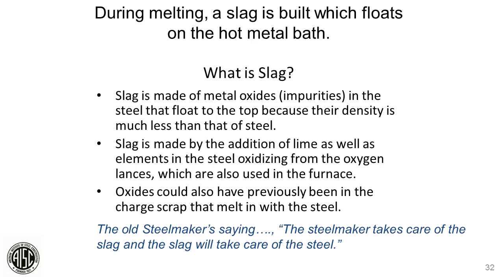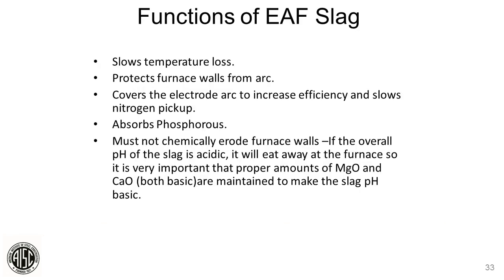So basically it's metal oxides, impurities in the steel that float to the top because they're less dense. We add lime, and when we say lime, we say high-cal lime and dolomitic lime, to get the chemistry of the slag that we want, and so absorb the impurities in the steel that float to the top. And oxides that should have previously been in the charged scrap meld in with the steel. That's where they could come from. They come from that as well. So we'll talk about the slag process in the next slide. So that's multifunctional, very crucial.